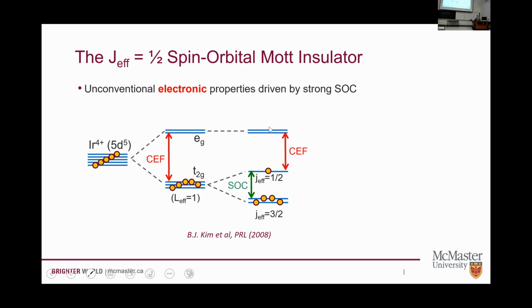Okay. So one of the things that can happen when we have this strong spin orbit coupling is we can get unusual electronic properties that we wouldn't ordinarily see. And so the classic example of this is something called the J effective 1/2 spin orbital Mott insulator. So the J effective 1/2 here is a total effective angular momentum. So this is basically the magnetic moment or a composite spin and orbital moment that these systems display. And this Mott insulating state is one that sort of emerges unexpectedly in these iridium-based compounds.